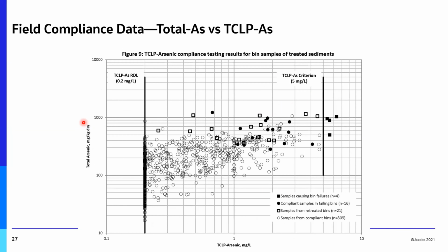This is the bin compliance. So here is your total arsenic in terms of milligrams per kilogram. Here's your official TCLP arsenic. And so what we had here was, again, I said any single value over 5 milligrams per liter created a fail. We had 4 of those, which then meant that we had to reprocess the entire bin, even though 16 of those samples were compliant from those same bins. Didn't matter. You had 1 failure, reprocess.